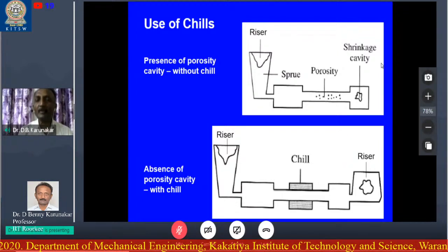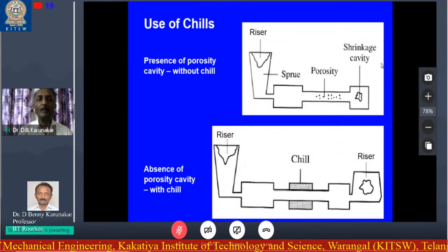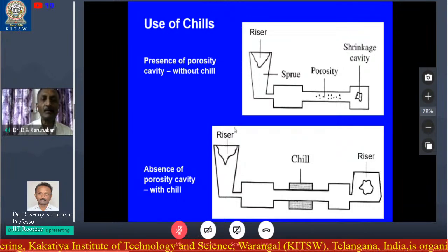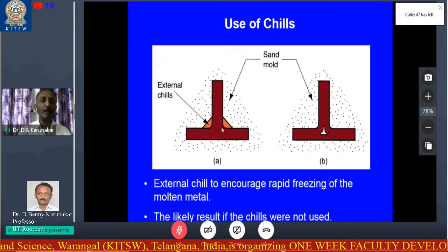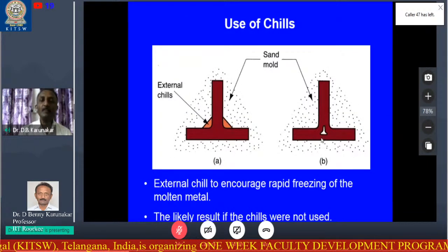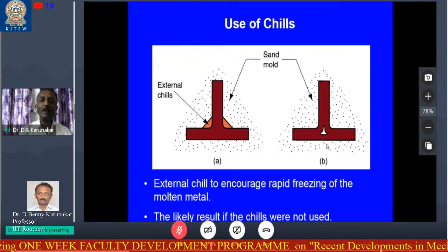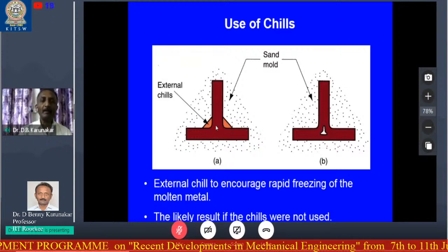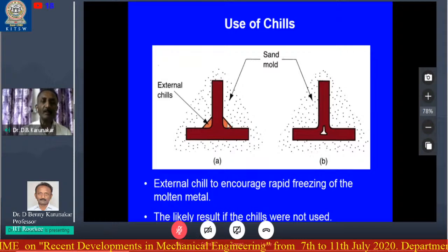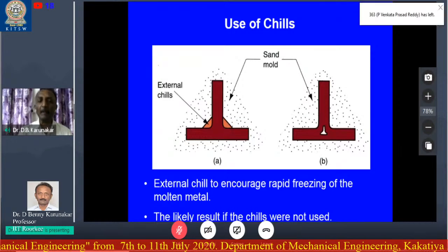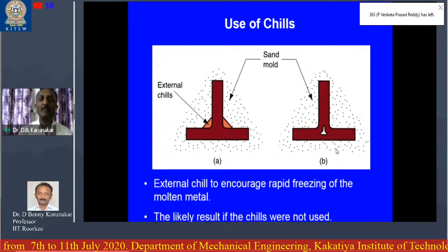So we have to prevent this. For this purpose, we can use chills. Here again we are using chills. In the absence of chills, there will be a shrinkage defect. Why? Because this portion is taking larger time for solidification, and when you use chills here, these chills are metallic pieces, so they absorb heat rapidly and ensure there is no shrinkage cavity at the center.